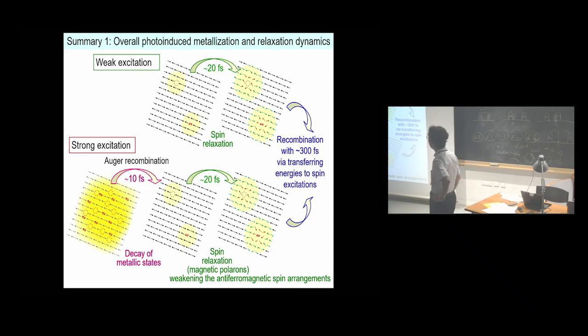And the first transition from the first panel to the right is response to what exactly? Excitation is performed beyond the Mott gap. But when the excitation density is very small, the metallic state cannot be formed. Okay, so the small number of carriers cannot freely move. But in the other case, the carrier number is very high. So in that case, the metallic response is observed. Okay.